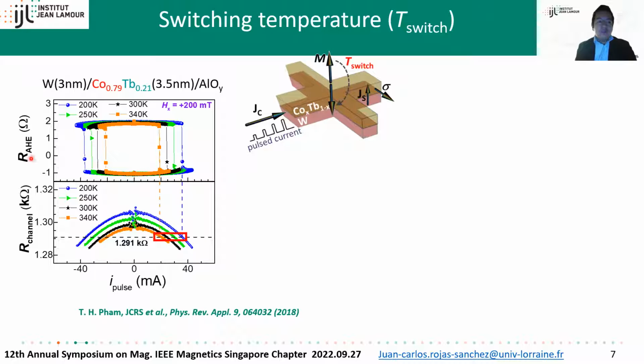At the top, we have the anomalous Hall effect measurement, so this current-induced switching experiment. At the bottom, we have the resistance of the channel measured under the same conditions. We can see the parabolic behavior because of the heating effect. And if we follow this vertical line, we can see that for different initial cryostat temperatures, we reach the same level of resistance. That means that the device reached the same temperature.